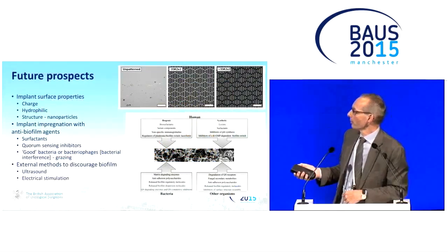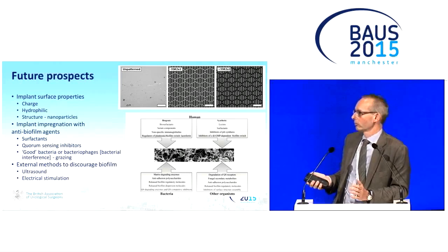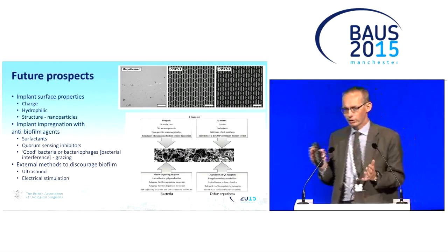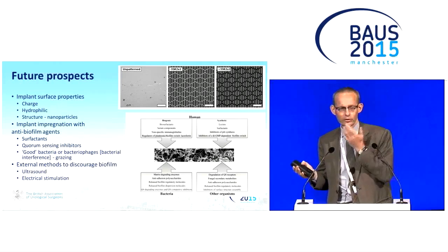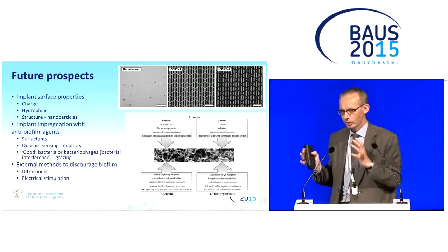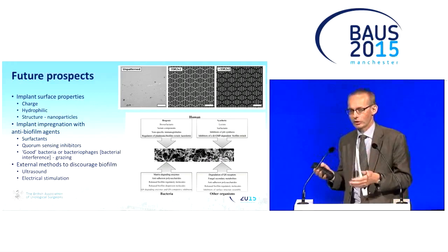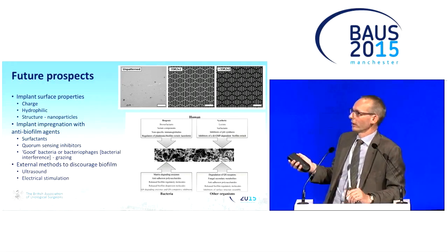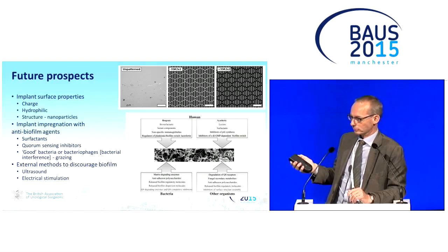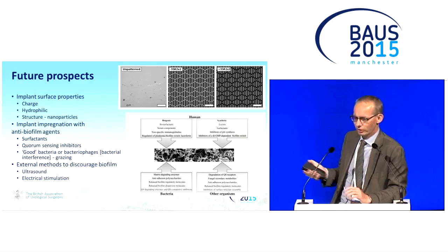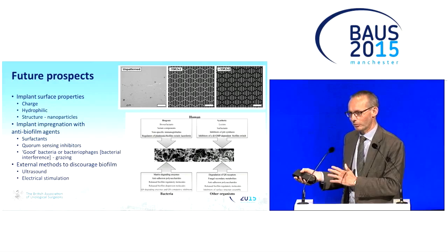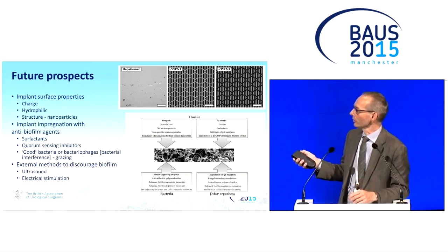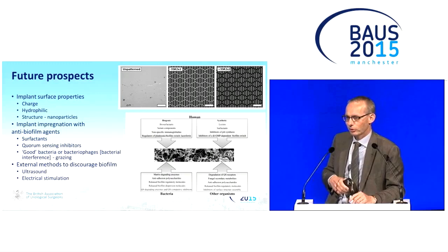So one thing you might be hearing about is surface, so again material technology. In the past the key was to try and create a smooth surface. That was why there was so much excitement 50 years ago with silicone, because it's quite a smooth surface compared to latex, which has a number of random imperfections. But more recently it's been found that if you have regular imperfections, so this is nanoparticle science, these are under very high EM magnification. This is so-called shark skin, because it came from an idea that sharks don't seem to get barnacles, whereas whales do. And if you look at the difference, shark skin has this type of microscopic pattern.